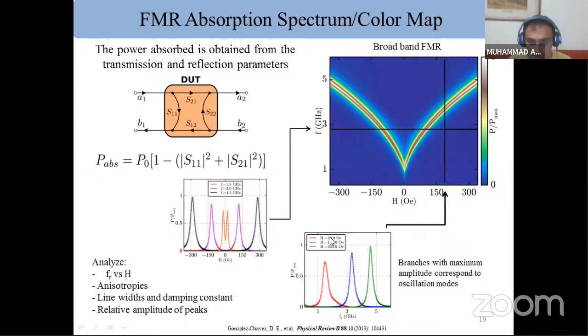Sweep the frequency. Here we get a scan, fixing the field at 20, then 150 and 300, with branches of maximum amplitude corresponding to the oscillation modes in a magnetic material. We can analyze anisotropy in the system with the help of a color map, line width and damping constant.